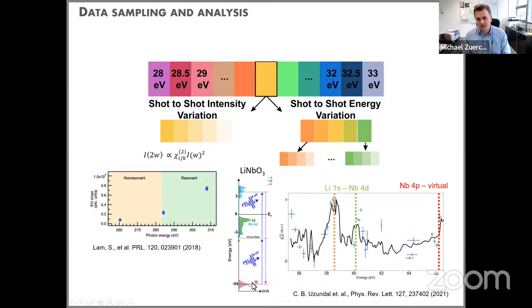So just for the energetics, we use in this case the FEL tuned to 29 electron volts. So we go resonant with 2 photons to the lithium K edge in this case, in this material. And this is the measured and calculated second harmonic spectrum. With second harmonic spectrum, what I actually really mean is the Chi2 depending on photon energy. And what you can see here are certain resonances.